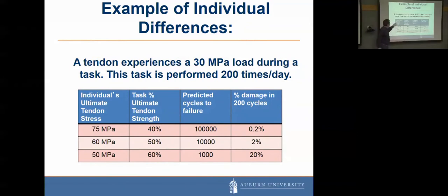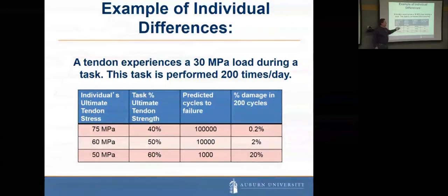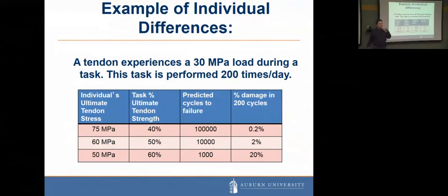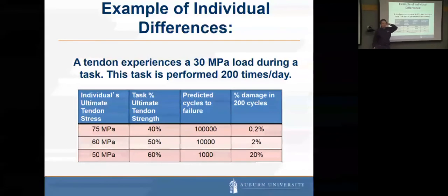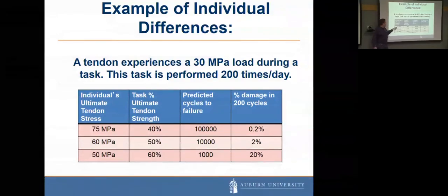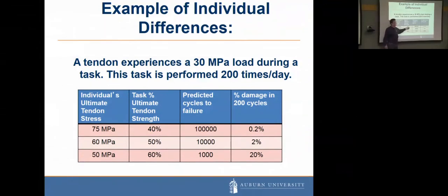So let's say that somebody's ultimate tendon stress was at 75 megapascals, and they're exposed to a 30 megapascal stress during a work task. And let's say that task is done 200 times during the day. Well, if they have an ultimate strength of 75 MPa, they're going to be working at about 40% of their tendon tissue strength. Predicted cycles to failure would be about 100,000. The percent of damage done in 200 cycles is going to be about 0.2%. As this worker ages, his tendon strength is going to go down to maybe 60 MPa. Now if he does the same job, he's working at 50% of his ultimate strength, so fewer cycles to failure and a higher percentage of damage being done by the same task.